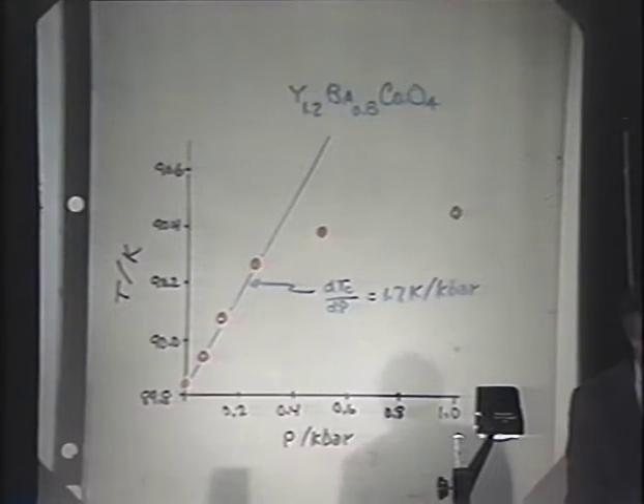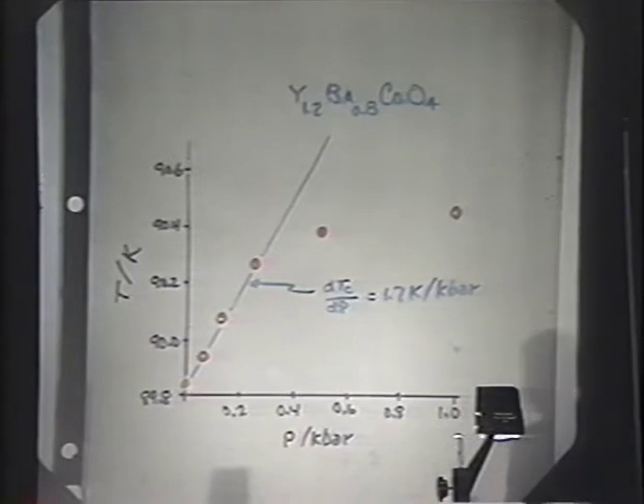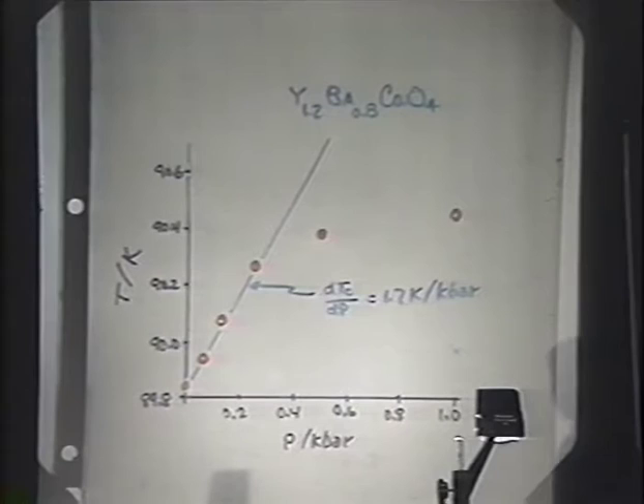So our picture is that we have this compressibility collapse occurring at a very modest pressure of about 3/10 of a kilobar. And so what's going on in this material is we're sitting right on top of this second order phase transition, with its attendant soft modes and instability, presumably then contributing to the electron-phonon interaction and causing the 90-degree superconductivity in some sense.